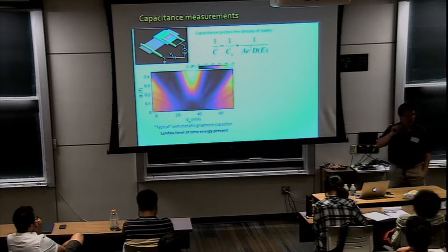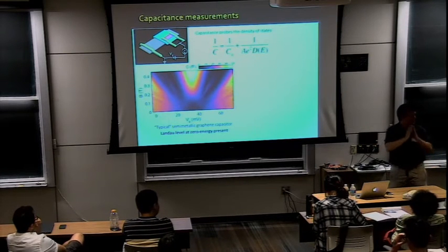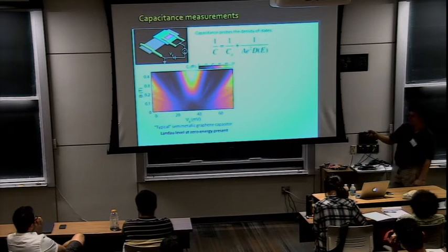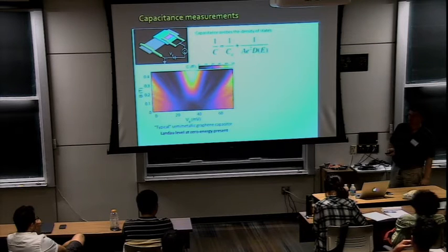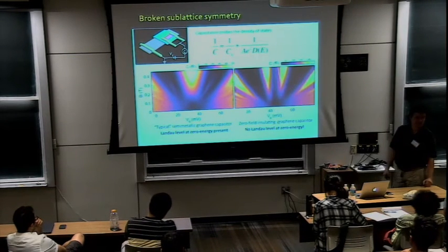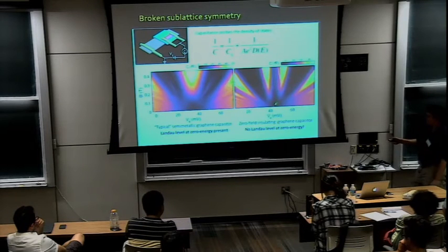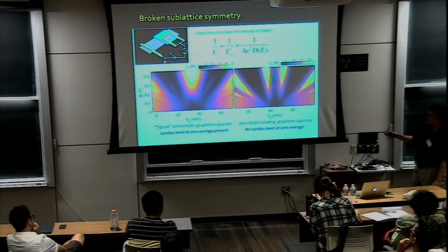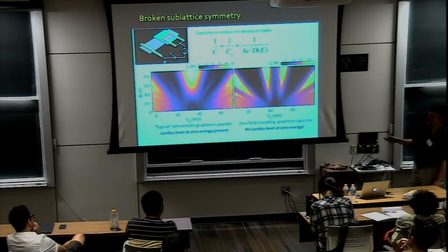But as you increase the magnetic field, the zero Landau level appears. It's a peak in the density of states. For the zero Landau level, that's this bright thing. This is the appearance of the zero energy Landau level in graphene, measured directly by measuring quantum capacitance. This is for graphene with a large twist angle with respect to the BN. If we have a small twist angle, this is what you get. Okay? You can see a dip at zero, but the zero energy Landau level never forms. You get a split peak.